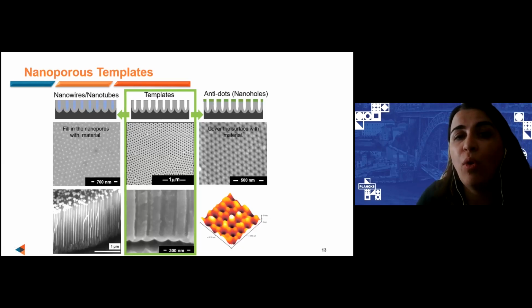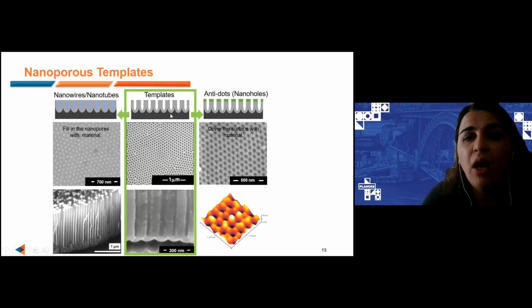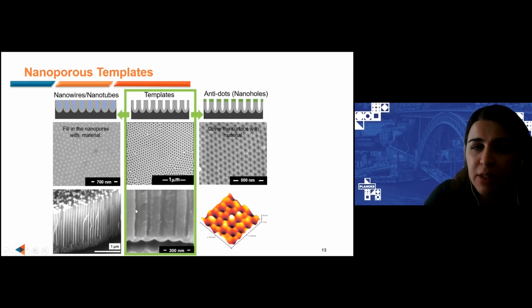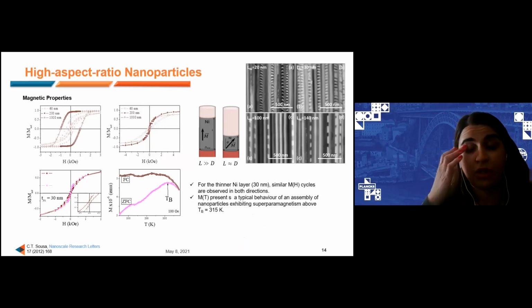So, to grow our magnetic and plasmonic nanostructures, we use a template-assisted method. We start to oxidize an aluminum foil, and in specific conditions, we obtain aluminum oxide, a nanoporous aluminum membrane with pores where we can control the diameter and the length of these pores to have the desired dimensions. Then we can fill these pores with the desired material and grow inside these pores our high aspect ratio nanostructures.